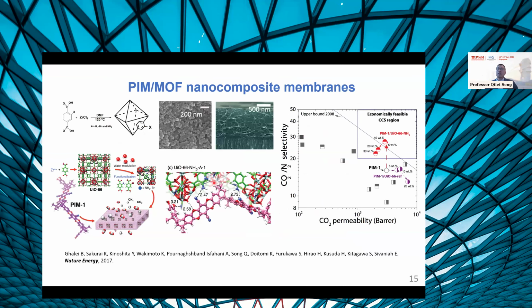Another study I want to briefly discuss is that we also developed PIMs with functionalized metal organic frameworks, including UiO-66. By tuning the interaction between the polymers and the MOFs, we were able to enhance the selectivity, because this interaction can rigidify the polymers and enhance their rigidity. So then we can improve the selectivity. For example, the CO2/nitrogen selectivity of the PIM-1 and UiO-66 membrane can be improved to around 30.